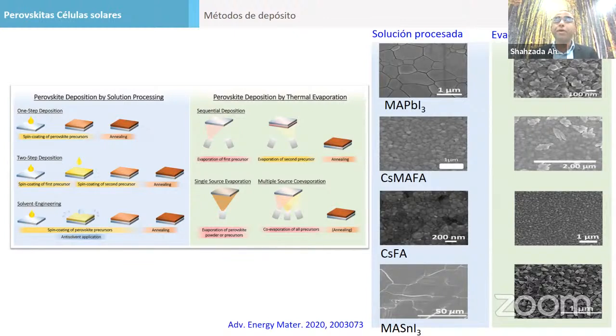We can evaporate the perovskite. We can sublime it. You can evaporate perovskite thickness, and this is also very good because if you evaporate the perovskite, you can exactly control the thickness. The device reproducibility will be very, very high. In wet chemistry techniques, we cannot exactly control the thickness to 2 nanometer resolution.